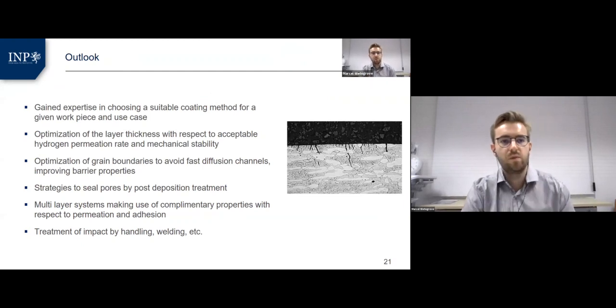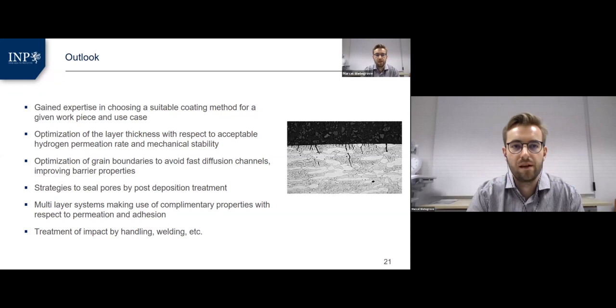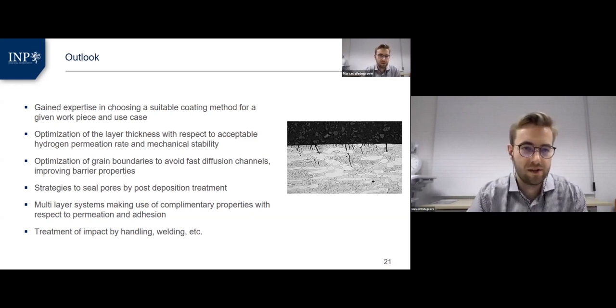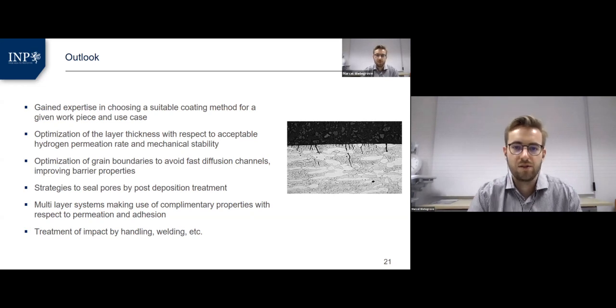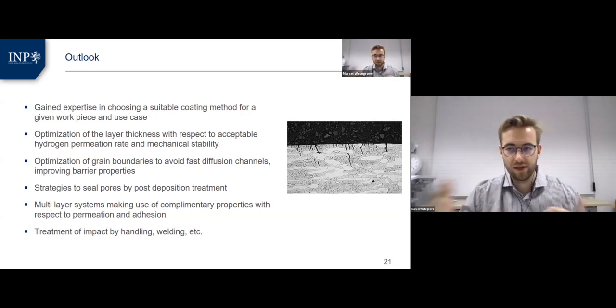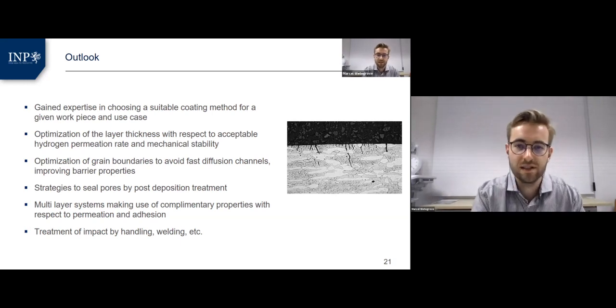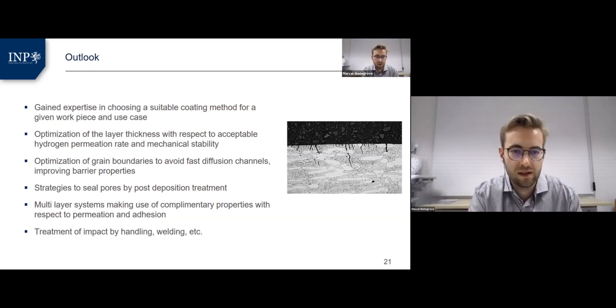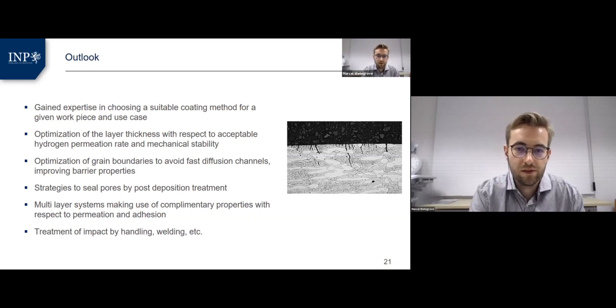To sum up my talk, what are the goals or the hopes and plans for our project is first, of course, to strengthen our expertise in choosing the suitable coating methods with respect to the given work pieces and use cases, to optimize the layer thickness with respect to acceptable hydrogen permeation rates. In this case, of course, thicker coatings are always desirable to achieve lower permeation rates, but on the other hand, thin films are more favorable with respect to mechanical stability, to optimize grain boundaries in pursuit of avoiding fast diffusion channels and thereby improving barrier properties.